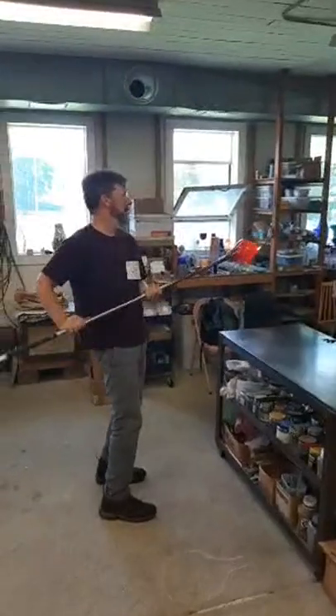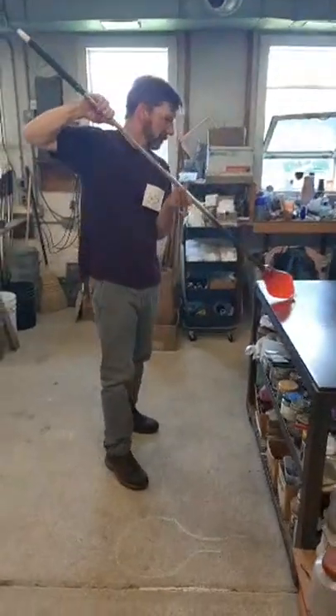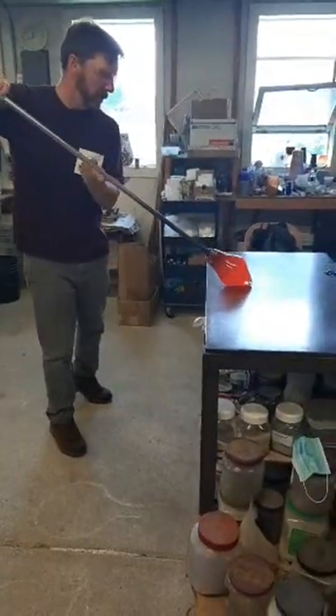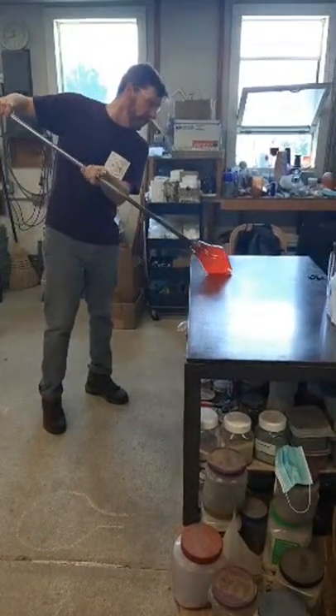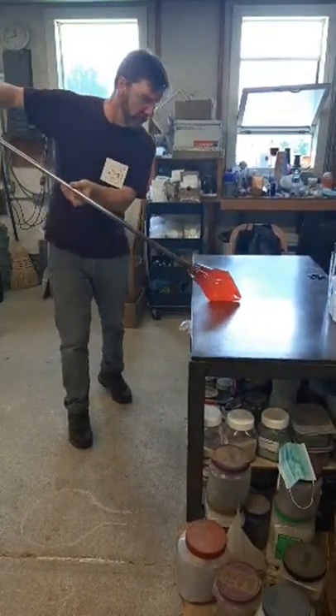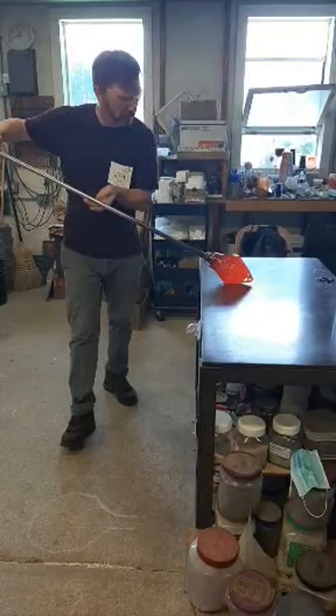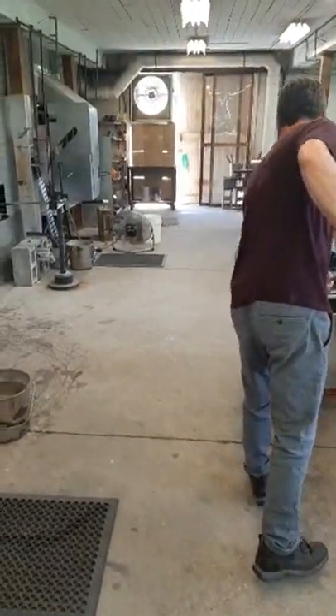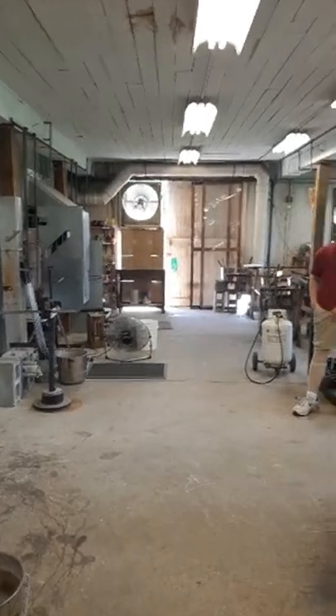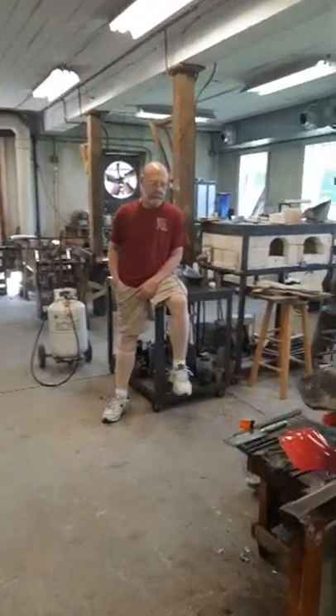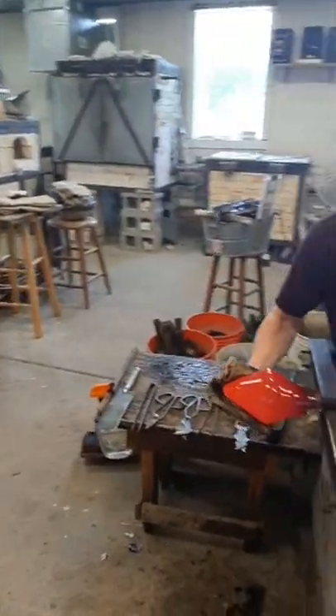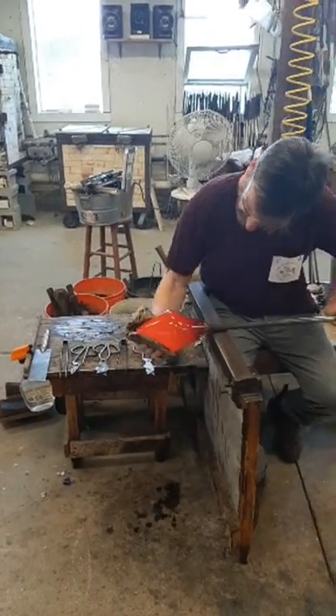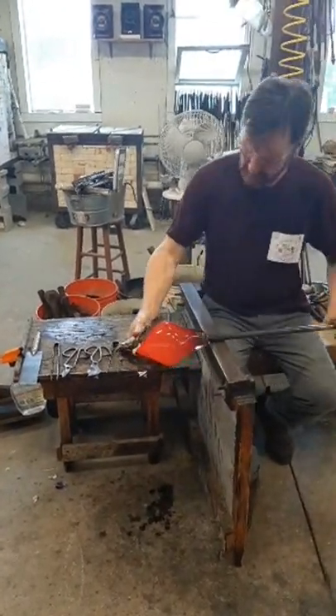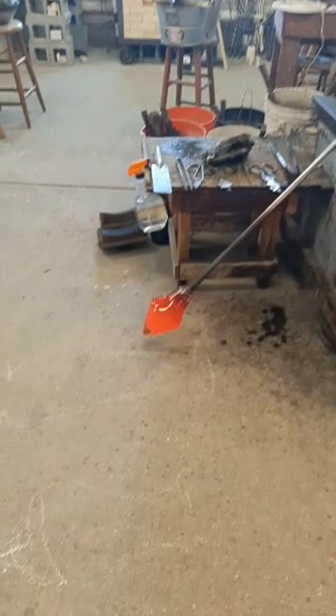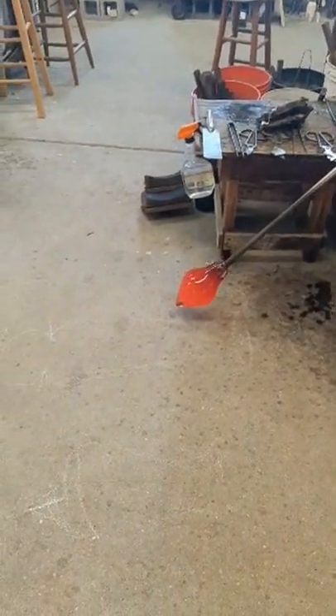A glass blower has many tools to choose from. When he points it up like that, the glass actually gets shorter. Notice how only the very end of the glass is touching the marver. That's what's getting cooled right now. So you may ask, what about chill marks on that? Those will come out during subsequent heats. If Todd had left the chill marks on the intermediate layer, that's what would have shown up as a haze.